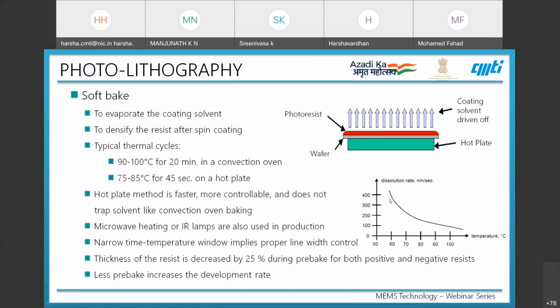The thickness of the resist is decreased by about 25% during the pre-bake for both positive and negative resist, which implies that less pre-bake increases the development rate.